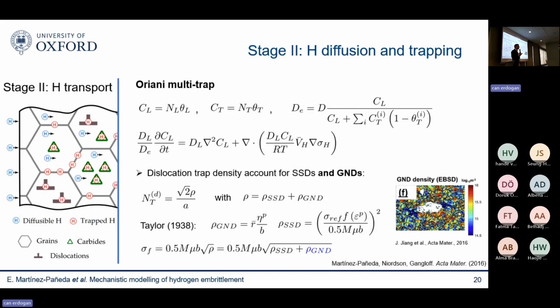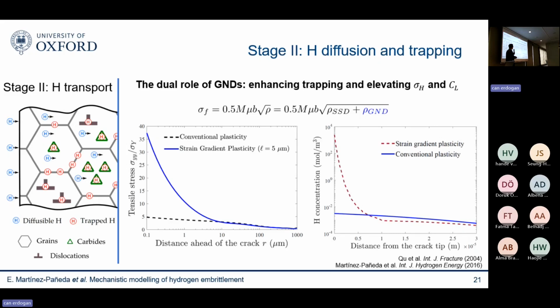And they play a big role in hydrogen, not only if you want to quantify how much hydrogen you have in your dislocations, but also because, as we heard in the previous talk, GNDs play a big role in strengthening and hardening methods. So we know that GNDs will act as obstacles to other dislocations, and that elevates stresses. And this is something that people have seen through a wide range of microscale experiments. And the implications in fracture mechanics is that if you look at your stress inside of your crack, what you see is that far away from your crack, basically you can capture these GND effects through appropriate constitutive models, like